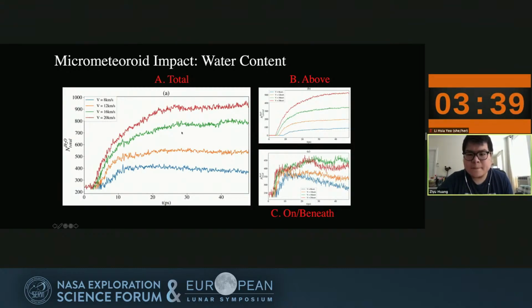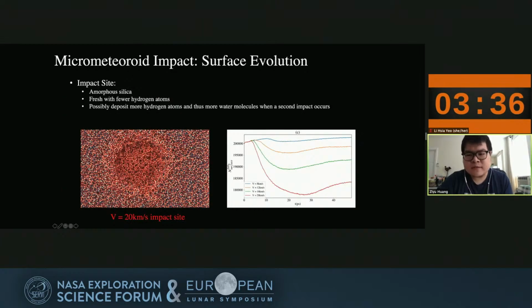And when we look at the impact site, we found that the post-impact site is becoming amorphous and also porous. The figure on the right shows the silicon oxygen 4 tetrahedra, and it shows a significant change of the surface atomic structure. The impact removed the hydrogen on the surface, making the surface fresh again, and this could be ready for another implantation cycle. And also the amorphous structure makes it possible to deposit more hydrogen atoms in the implantation, and thus more water molecules could be formed when the second impact occurs at this post-impact site.